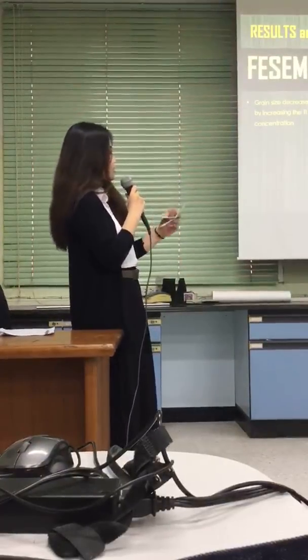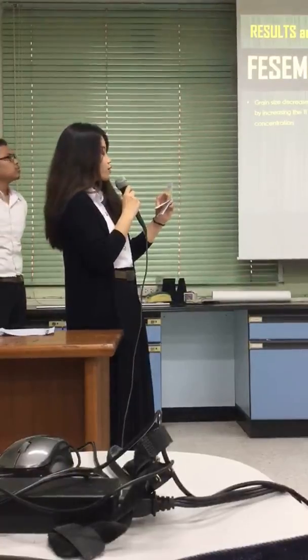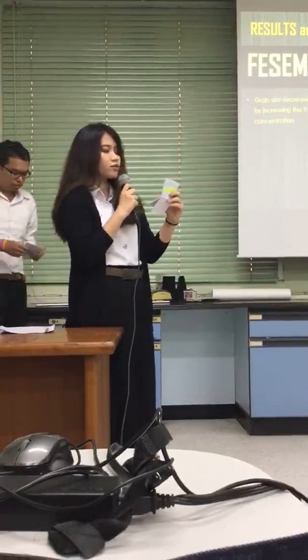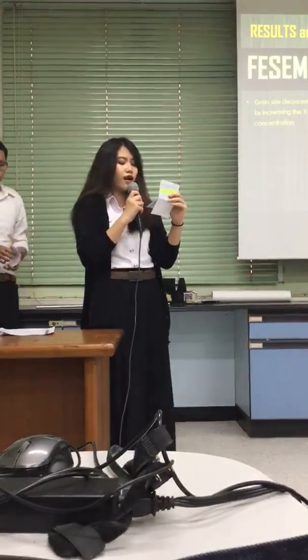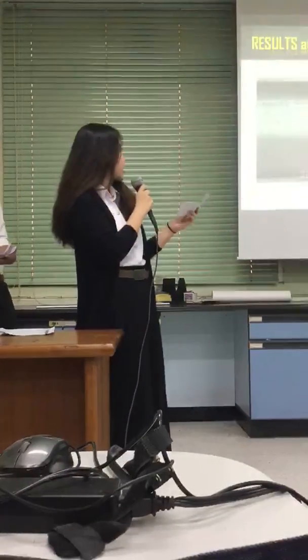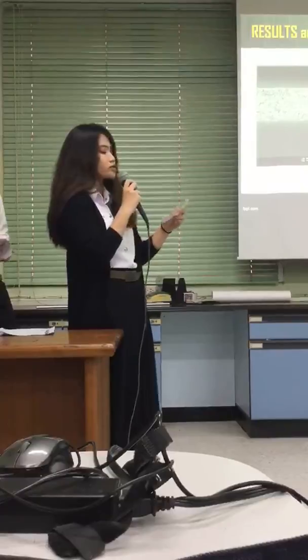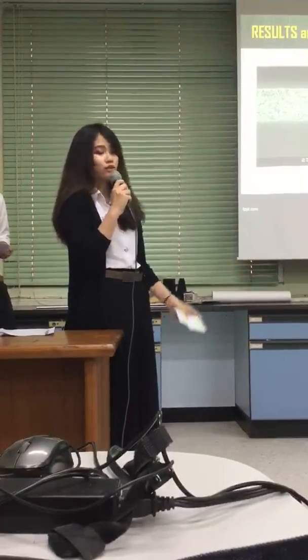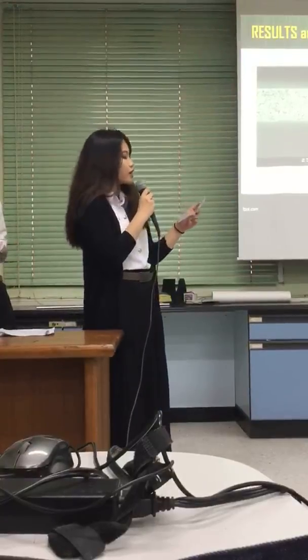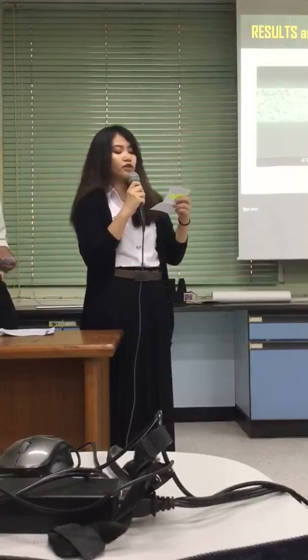Figure 11 shows the surface of samples with different titanium concentration. We found that mean grain size decreased with increasing titanium because titanium incorporated in zinc oxide structure may tend to create more nucleation centers. Next is cross section of sample with 0.2 atomic percent titanium concentration. The surface is uniform and compact with columnar structure. The thickness is 220 nanometers, but we will explain further about that in ellipsometry analysis by Mr. Shashna.